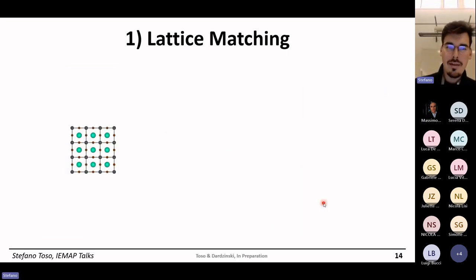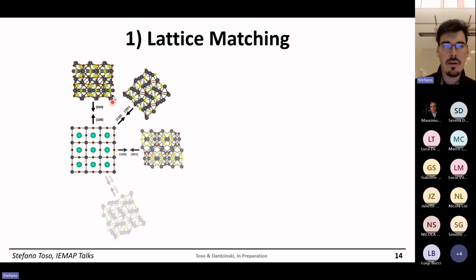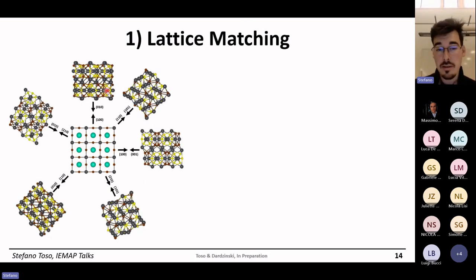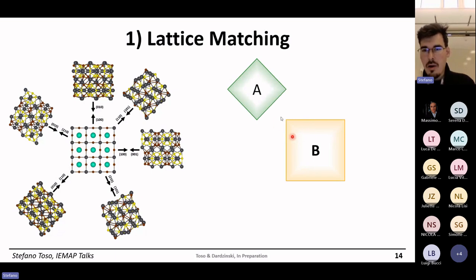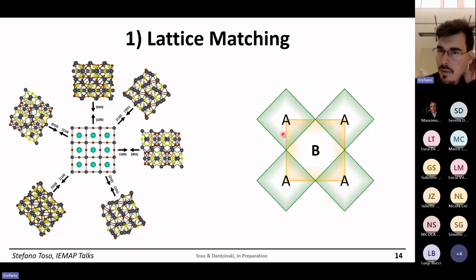Now, when you move it to a real three-dimensional problem, the same situation occurs. You have a base material that in our example is the perovskite, and your other semiconductor that we call a chalco halide. You can attach it in different directions that are identified by Miller indexes. Again, you have to find how these two materials will match. At this point, we are in a bidimensional situation, so these are actually the surfaces of the two materials. And you have to find a situation where the same symmetry operations will describe properly both materials. If you manage, then you have an epitaxial match.